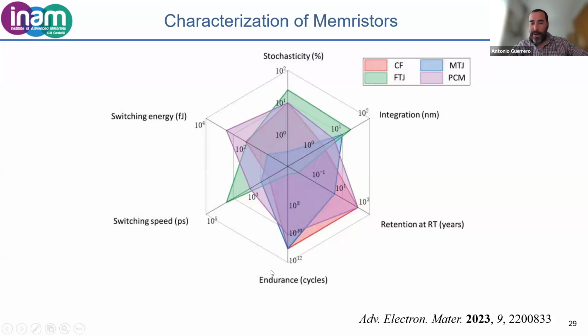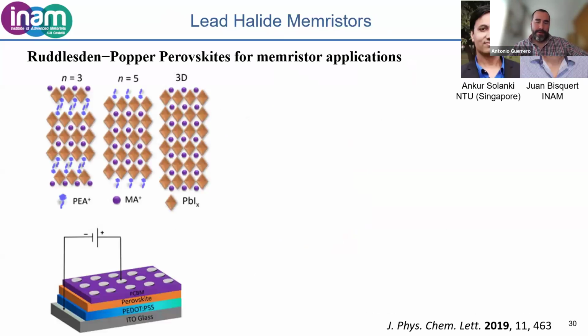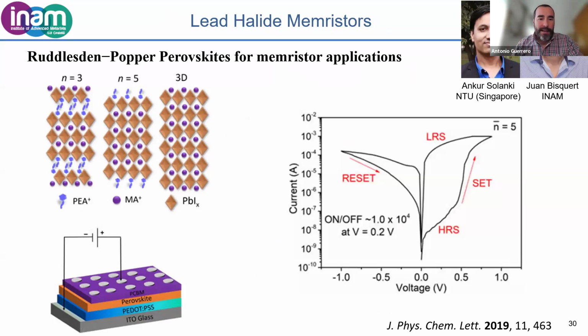So we can do different cycles, and we want them to be as stable as possible with the number of cycles. Okay, so now I will go fast. I will just give you some examples on how we can tune this hysteresis, this IV curve I just explained to you. So this is one of our initial works in 2019. We use a perovskite with an external layer of PCBM and silver contact.